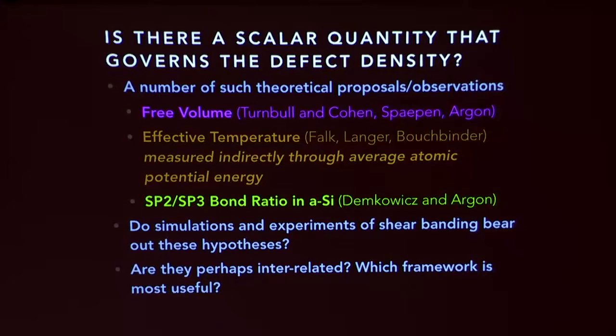Clearly it can't only be a scalar quantity at work here. The fact that we have the Bauschinger effect must mean there's some tensor part of the local state variable. But what I'm saying is that in the literature already there's this idea that perhaps there is a scalar quantity that, if it doesn't describe the orientation of the STZs, at least gives their density—gives an idea of how many there are.